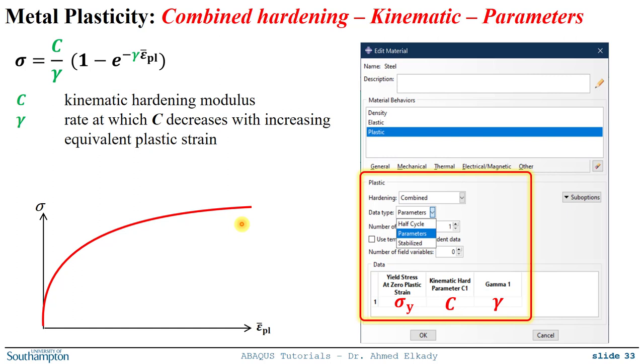Now, a couple of things to note here. This is not very easy to do because the same curve can be obtained by several combinations of C and gamma. So if you do this calibration, what you are getting is not really a unique solution. Just keep that in mind. But as long as you are getting the shape of the curve that you want, then you can input these parameters over here.